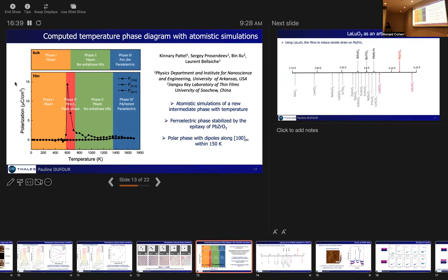But the origin could stem from maybe a residual compressive strain in our films, since it's not observed in bulk. So yes, I would say it's from strain. Also, it was shown that the stoichiometry of the films can also affect this emergence of an uncompensated dipole. So it could also come from a not fully stoichiometric composition in our thin films.